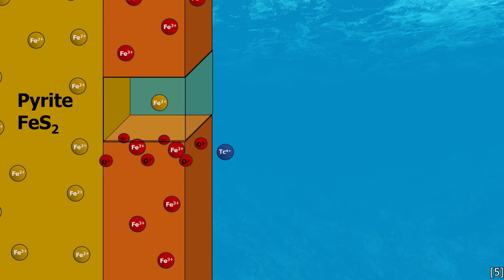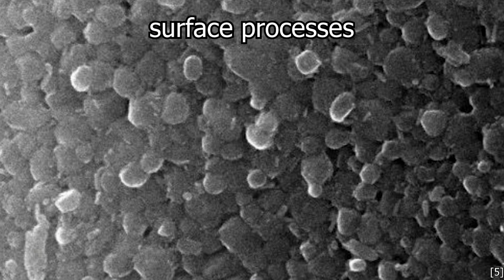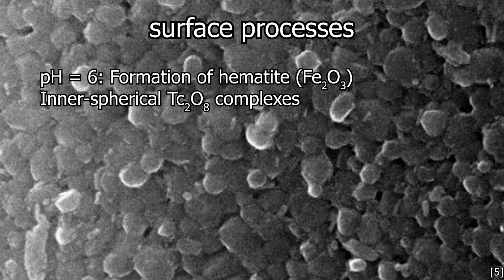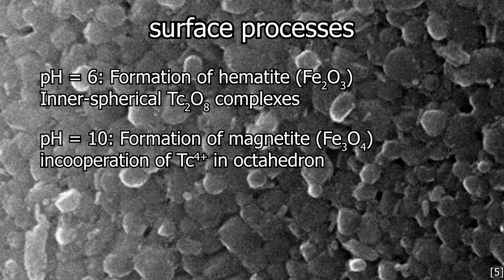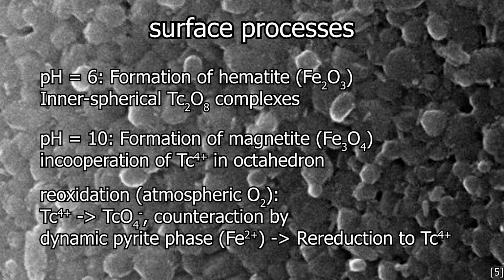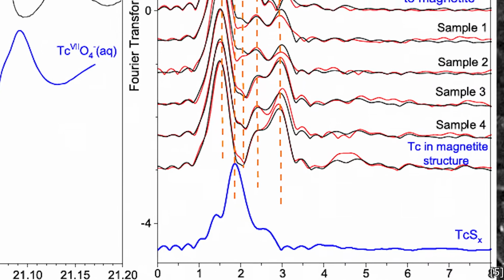This also means that if oxidative processes in the environment oxidize the immobilized technetium 4+ to pertechnetate again, which should then be released, this dynamic surface, which is not passivated, provides a constant reservoir of iron 2+ that can reduce the technetium back again, allowing this to be present as technetium 4+ and be incorporated even more stably into the newly formed magnetite phase. A lot of cool stuff.